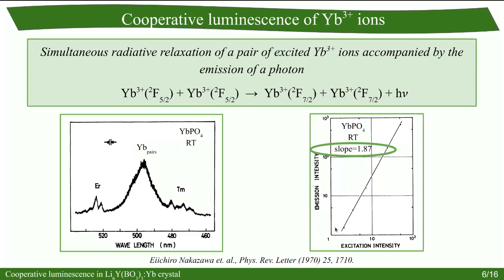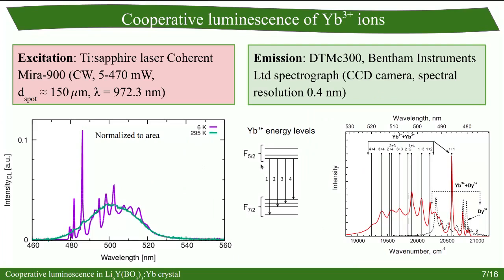we found that they measured 1.87 or a lot of types of exponents from 1.6 up to 2 values. In our measurement, we used a titanium sapphire laser, a continuous wave laser, whose intensity can be changed from 5 up to 470 milliwatt.